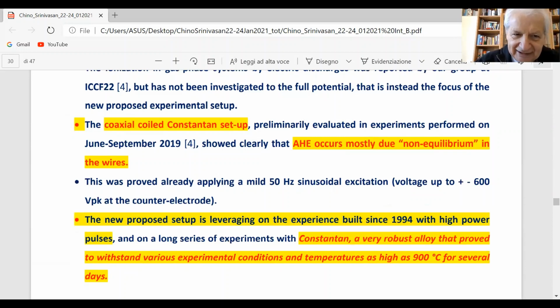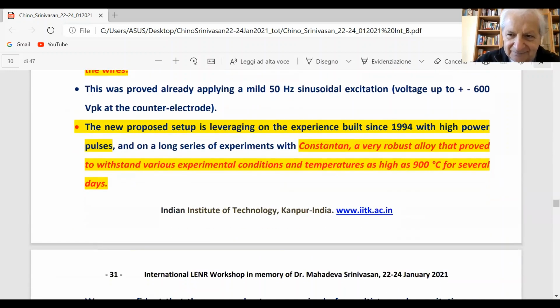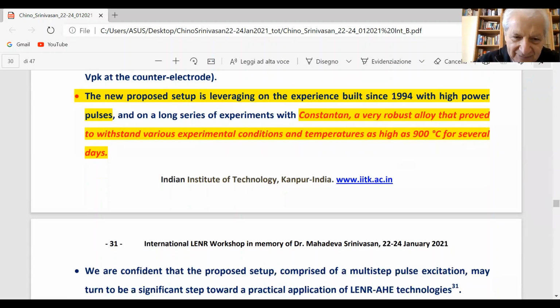Just a reminder about the constantan coil, which is specialized to have non-equilibrium condition along the wires. We have experienced it with 50 hertz excitation and it gave positive results. But now we can work up to 900 degrees, just because of constantan and not only 100 of palladium. So from a technological aspect, it's a big jump.